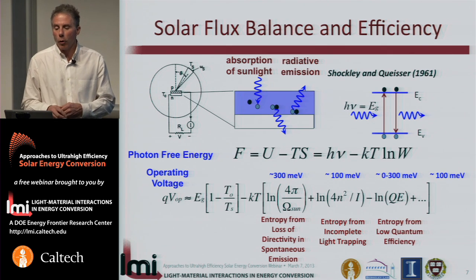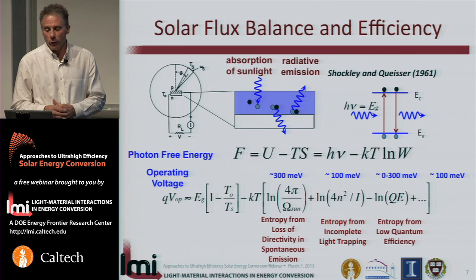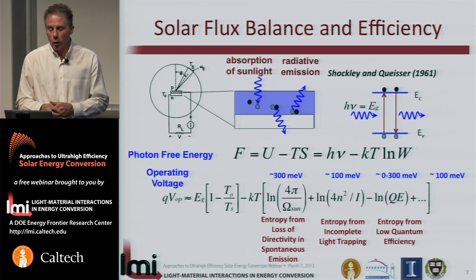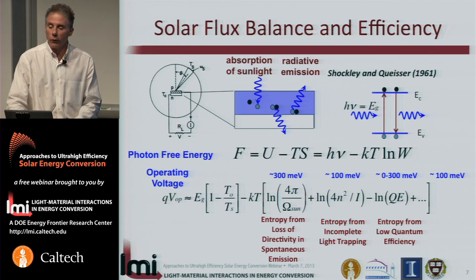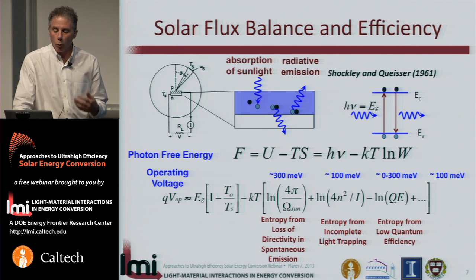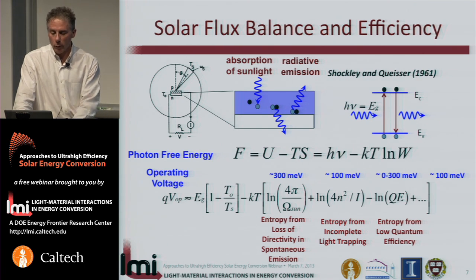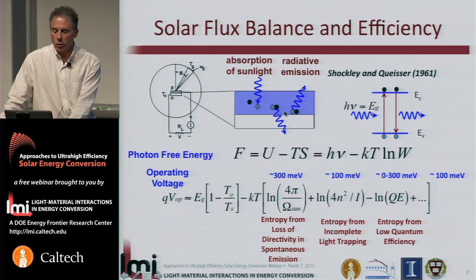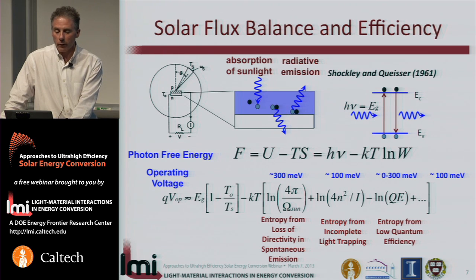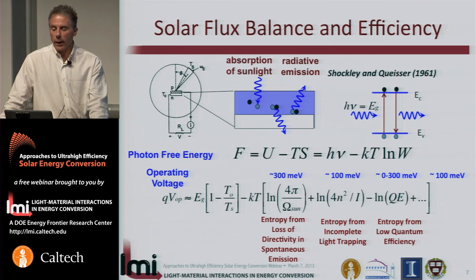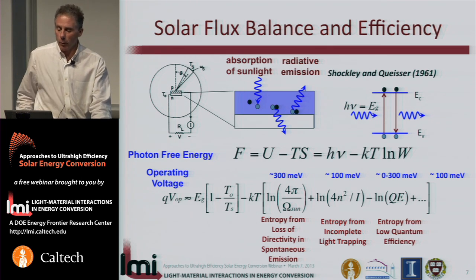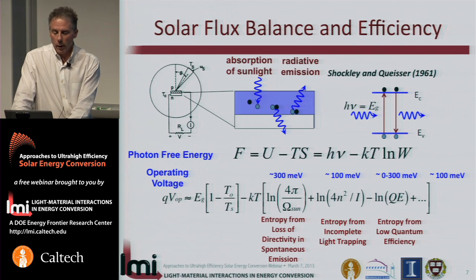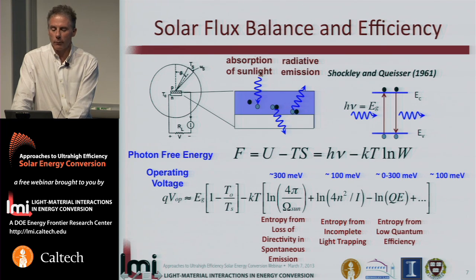If we think about using very high quality materials such that all of the non-radiative centers are removed by good crystal growth and purification of the material, such that the photovoltaic material is in the radiative limit, where the primary recombination process, or essentially the only recombination process of significance, is radiative emission, then as was done originally by Shockley and Queisser in their detailed balance picture, the absorption of sunlight that we can accomplish in a thin film cell or a crystalline cell of this kind is limited or dictated by the detailed balance between the absorption and emission of sunlight.